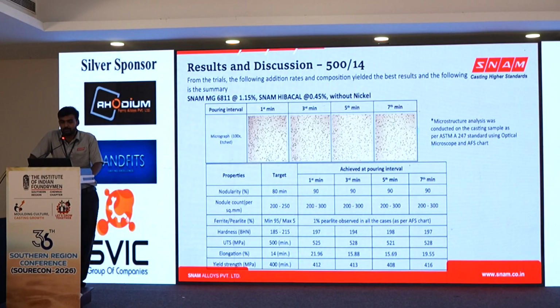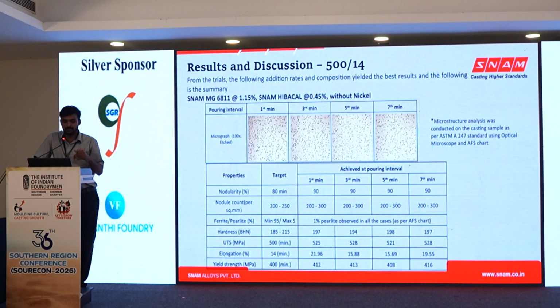Similarly, we have tried to produce 500/14. From the trials, this combination gave the best result. The combination is as follows: Mg6811 at 1.15% and Hybecal at 0.5%. When we try to produce 500/14 without nickel, we have achieved all the mechanical properties.